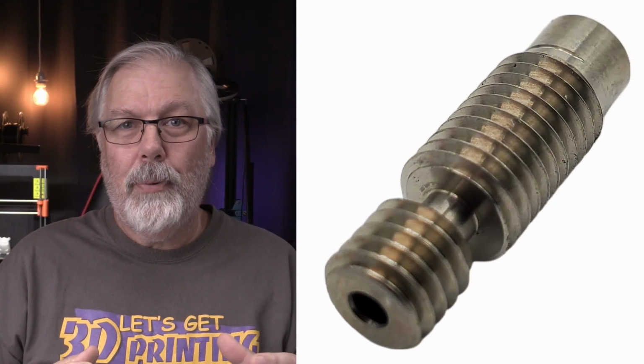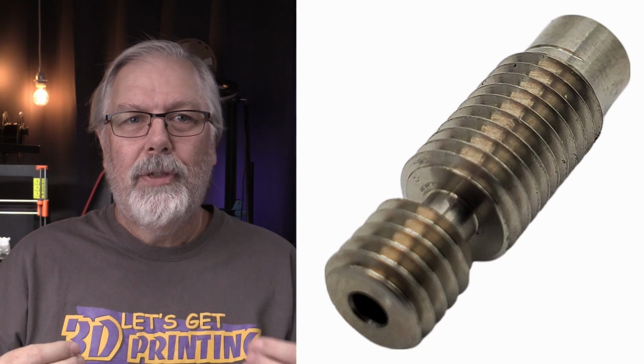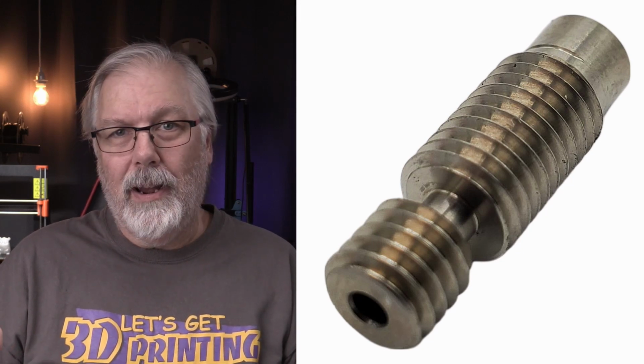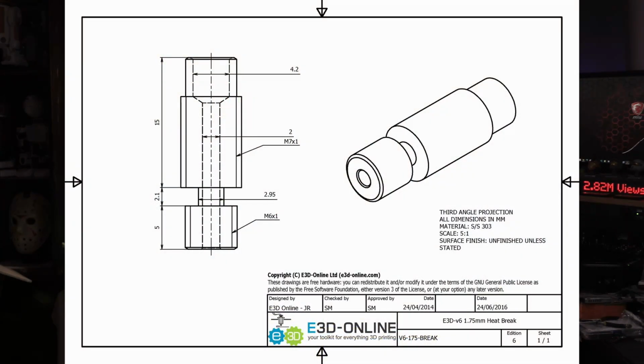The more permanent solution is to change the heat break to a standard E3D V6 heat break and add a silicone sock to the heat block. Why would you want to make these changes? The E3D V6 heat break has a consistent 2 millimeter bore, allowing the material not to get hung up after retraction occurs during the printing process. By adding a silicone sock, you can reduce the thermal shock to the block when your part cooling fan starts.